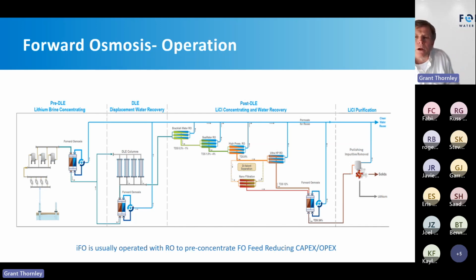However, remember that we're always looking at the economics of the DLE process. If there's some way of reducing the energy, the capex, or the physical footprint, and the opex, we want to do that. So what we do in FO is we typically use a reverse osmosis, maybe at a high pressure at around 1,000, 1,100 psi. RO operates at about 2, maybe 3 kilowatt hours per cubic meter of permeate. That will concentrate the feed, and by concentrating the feed, that reduces the volume going to the FO. Reduced volume going to the FO means that's less I have to concentrate or treat. That means a significant reduction in capex and opex.